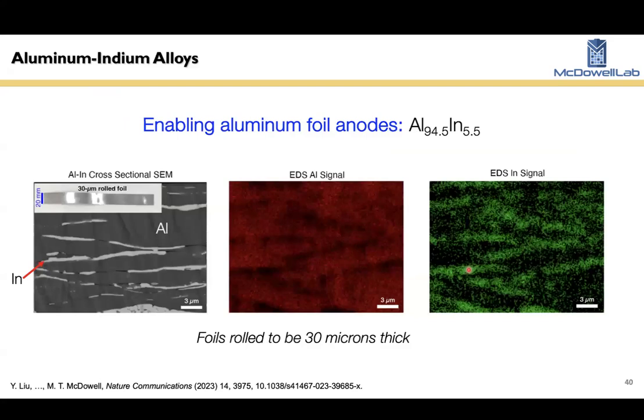So what we found is we've investigated these in solid-state batteries, and we found this particular material amongst a few other candidates to be quite interesting. So this is a material that's 95% aluminum and about 5% indium. When you make this alloy and roll it out, you see that there's a completely phase-separated microstructure. There's no alloying, there's no compound formation. Indium, the lighter phase here, is dispersed as these layers within the aluminum structure. And this happens to be a very useful microstructure for batteries.